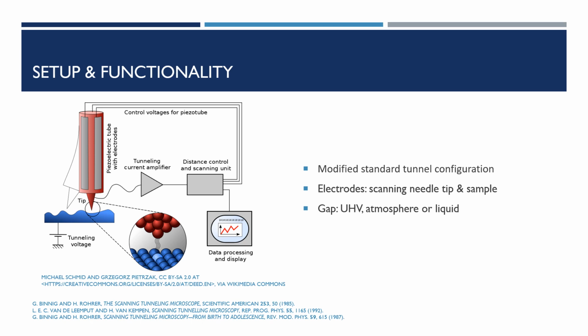The most commonly used tip materials are tungsten, platinum, or platinum iridium wires. The gap between is often empty, so ultra-high vacuum. It can also be filled with the atmosphere, but there is a problem that this contains oxygen, which can oxidize the surface or change the surface in other ways. The measurement can also be done in a liquid. The advantage there is that the sample does not change by contact with air. This is certainly the case for some biological samples whose natural environment is a liquid and which will collapse if it dries.